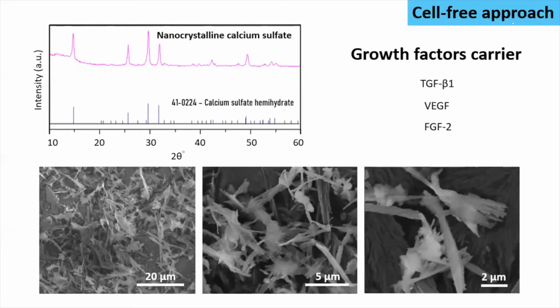First, we will talk about the cell-free approach. We tried to synthesize a nanocrystalline calcium sulfate by using cryovacuum technique. We can see the SEM pictures. The feather-like crystals have a high surface area in which the growth factor could be accommodated. And the X-ray also proved that this is calcium sulfate crystal.